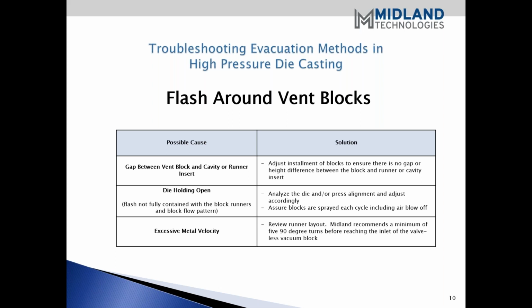Yes, that's right. And this is one of the big ones that we see a lot of, and complaints that people have, and we've seen it, and I believe we've made custom blocks with inserts in the tooth area where there's erosion, there's wear on the block itself. Those are all indications. Die casting 101, go right back. That indicates that the velocity of the metal when it arrives at that block is too high. Okay,